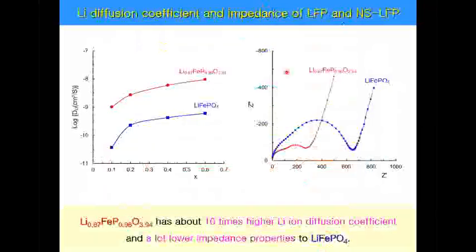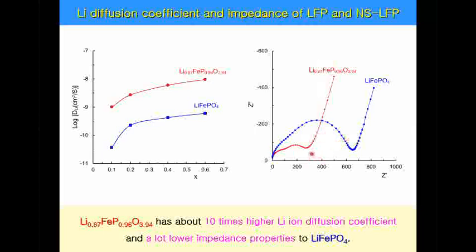We want to confirm whether there is a real increment of ion mobility when we remove some amount of oxygen. As illustrated here, the Li-ion conductivity over our LFP is 10 times or more higher than normal LFP, meaning our simulation and crystal structure study is well matched with real experimental results.